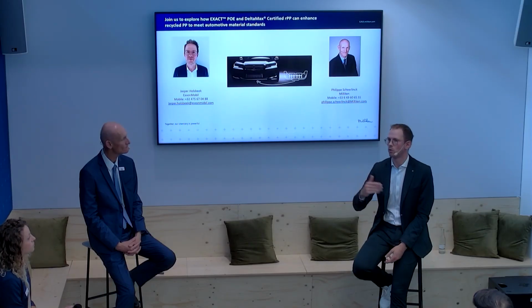So there the question is, what is the stiffness of your starting material, and what is the threshold that you're looking for? In this case, like Philippe already mentioned, we went really extreme, because we start at a really low quality, 100% recycled material. So to be able to push it to automotive standards, we had to go 20-25%. But it doesn't mean that you always need to use this kind of dosing. When you start using regular dosing, 5-10%, the stiffness will drop, but not significantly. So then you are still within the boundaries that are allowed in the automotive industry.